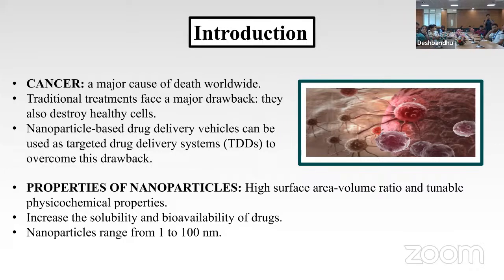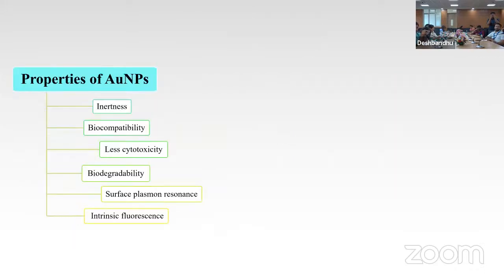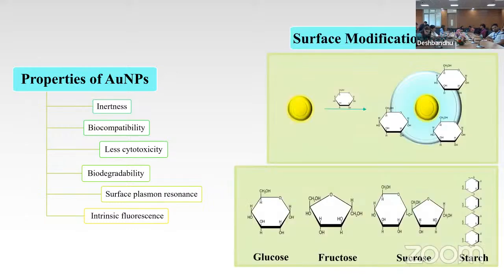Nanoparticle-based drug delivery vehicles can be used as targeted drug delivery systems due to their high surface area to volume ratio, with nanoparticles ranging from 1 to 100 nanometers. Among inorganic nanoparticles, gold nanoparticle-based drug delivery systems have been observed to be safe for in vivo use due to their inertness, biocompatibility, low cytotoxicity, biodegradability, surface plasmon resonance and intrinsic fluorescence. Bare gold nanoparticles are not stable, so to increase stability they can be surface functionalized with carbohydrates such as glucose, fructose, sucrose and starch. Carbohydrate-coated gold nanoparticles show good biocompatibility, which makes them suitable for targeted drug delivery.